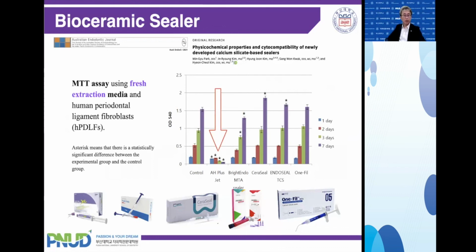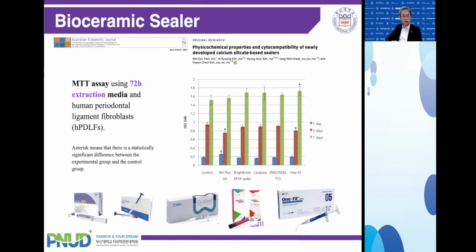So it's almost done. Here you can see the MTT assay. The epoxy resin sealers, as you see here, are indicated very low. The cell viability is not good. But the other calcium silicate sealers have good cell viability, even at the very early stage of sealer mixing. For the epoxy resin sealer, after setting, maybe 3 days later, the cytotoxicity comes down, but we can say that from the beginning, the calcium silicate sealer is very good for biocompatibility, or for the patient's initial adaptation when they accept the filling material. It's a very nice point of the calcium silicate sealers.